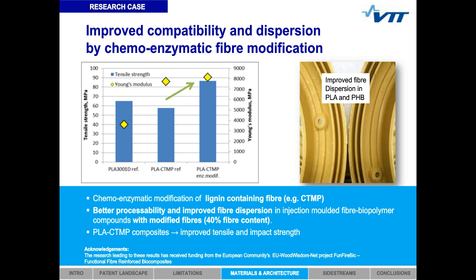So we had CTMP fibers that were first enzymatically activated and then chemically modified. And in the picture on the left-hand side, you see the impact of the chemical modification on the mechanical performance of the fibers. So you see, compared to neat PLA and the PLA CTMP composites without chemical modification, you see clear improvement after the chemical modification of the fibers, both in tensile strength and modulus. Additionally, the impact strength was improved. As a consequence of the improved compatibility, the dispersion of the fibers in the PLA and PHB matrices was significantly improved, as can be seen in the picture on the right hand side.